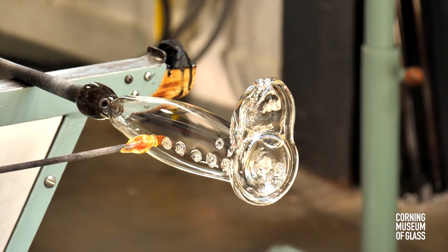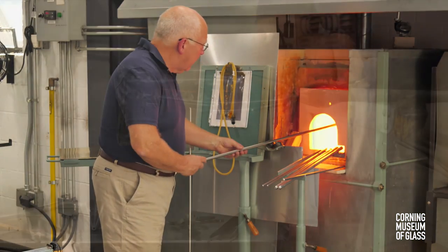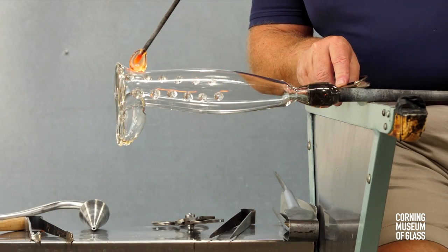Throughout this process, the entire boot is frequently reheated. It must all stay over a thousand degrees Fahrenheit, or it will begin to crack.